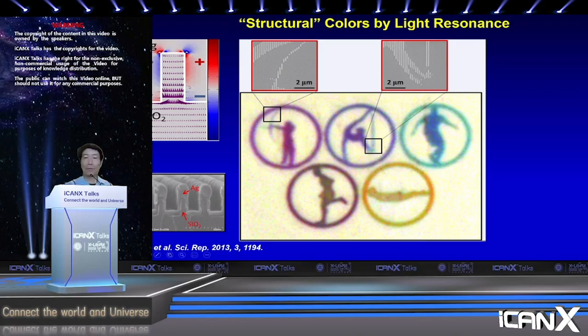So this may sound a little fancy, but I can give you a daily example that many people are familiar with. For example, if you play an instrument like the flute, the Chinese flute, you put your fingers at certain positions that give rise to different sounds. It is exactly the same principle. So your finger position actually determines this acoustic cavity length. We know the acoustic wavelength is on the order of tens or hundreds of centimeters. But with the same effect, the optical wavelength is about a million times smaller. So if you reduce that effect a million times, then you get this.